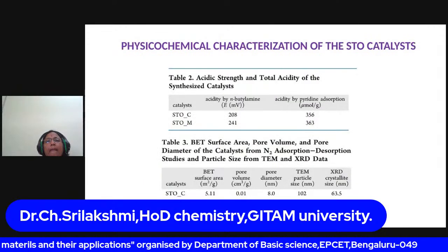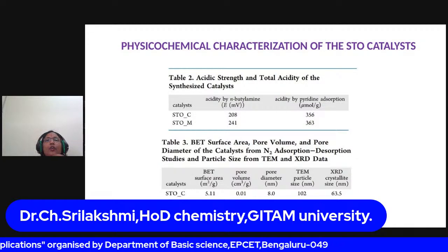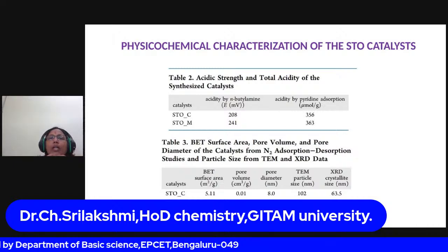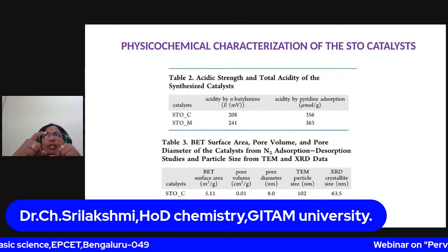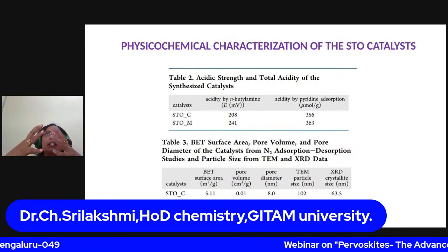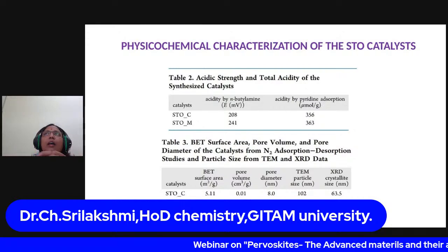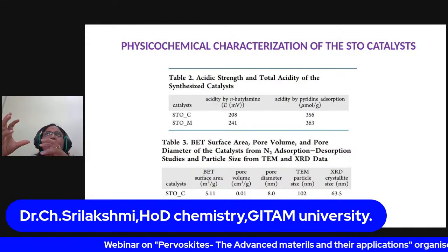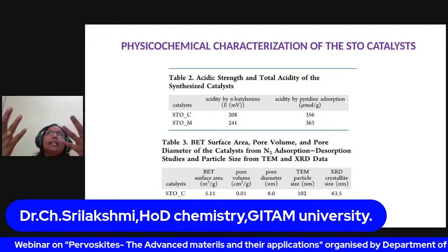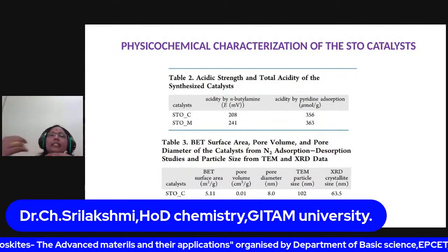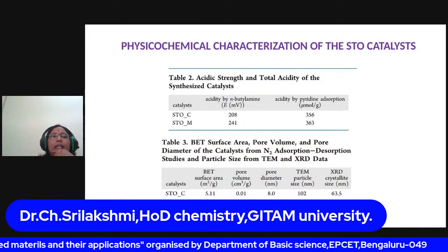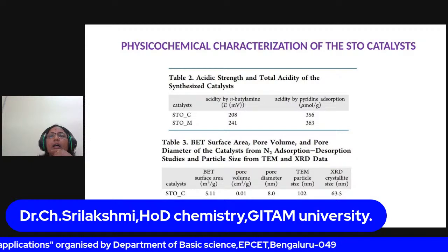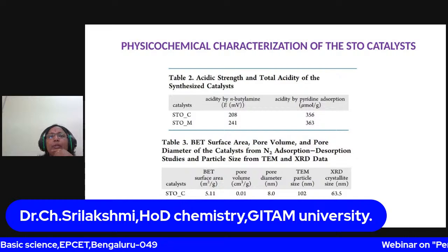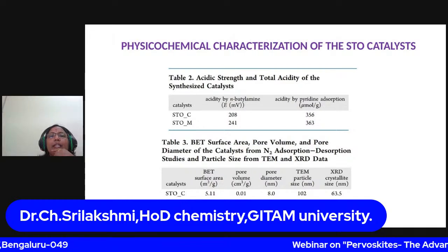And you can see the acid strength and total acidity. Total acidity is about the amount of Lewis acids or Bronsted acids. Acid strength is whether the acid sites are strong, moderately acidic, or weakly acidic. These are the two types of acid measurements we have conducted. One is to find out the acid strength. We have used n-butylamine titration, and we have used electrodes to measure the electrode potential.